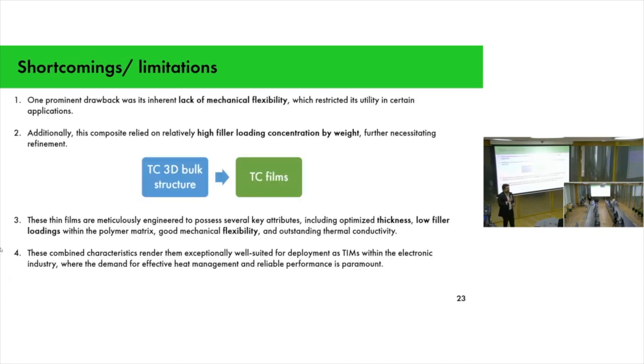But apart from these properties, we had some limitations and shortcomings. One prominent drawback was that it lacked mechanical flexibility and it used quite a high filler concentration of more than 66 weight percent. So we thought we should make a transition from the bulky 3D structure to thermally conductive films, which are more flexible and can reduce this drawback.